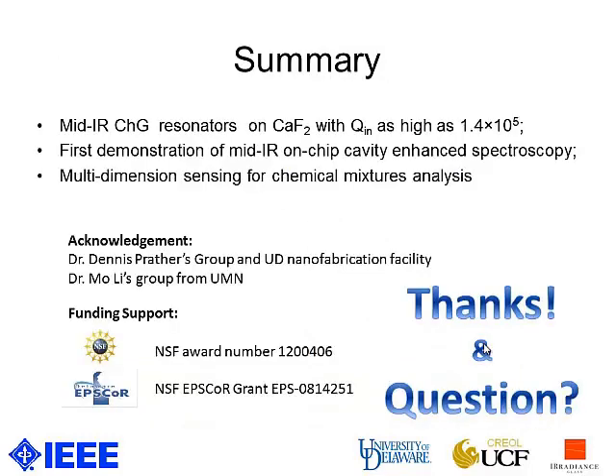In summary, we have fabricated mid-infrared chalcogenide glass resonators on calcium fluoride with an intrinsic quality factor as high as 1.4×10⁵. We also first demonstrated mid-infrared on-chip cavity-enhanced spectroscopy. These techniques enable multi-dimensional sensing for chemical mixture analysis. I would like to acknowledge the fabrication help from Dr. Dennis Prather's group from the University of Delaware and the UD nanofabrication facility, and also the silicon-on-calcium-fluoride substrate device from Dr. Mo Li's group from the University of Minnesota.